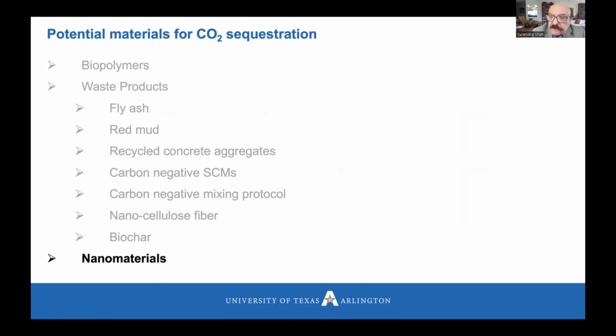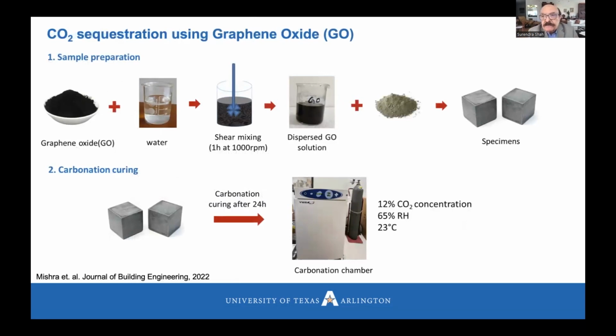As you know, many people have been working with nanomaterial, specifically graphene-based nanomaterials. And that includes carbon nanotube, includes graphene and graphene oxide. And people have shown that addition of this graphene-based nanomaterial, if they are well dispersed, they have many positive effects on hardened concrete properties. We have done a lot of work, for example, with very, very small amount of carbon nanotube, and it's shown a variety of improvement. So can graphene-based material also enhance CO2 capture?